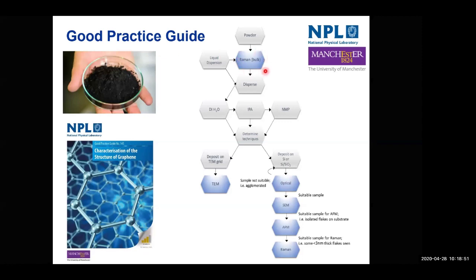Very simply, you go through an initial step to check with Raman spectroscopy. We'll go into detail on all these techniques in a minute. Using Raman spectroscopy, you understand that this material is at least graphitic, before then doing sample preparation to isolate flakes. You can look at the isolated flakes or particles themselves. Then there is a decision whether you go down the route of using TEM to do these measurements, or a combination of other techniques. But ultimately, what you're trying to do is understand the structure. You're trying to understand what these particles are like: the sizing, the thickness, and the disorder that's present, which again is a very important property, as we'll go through.